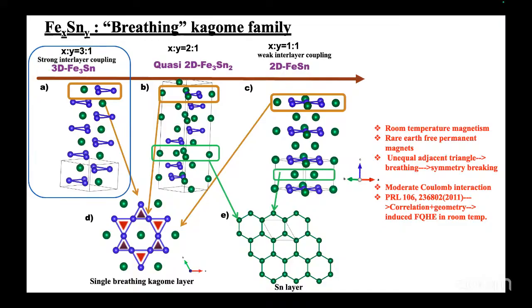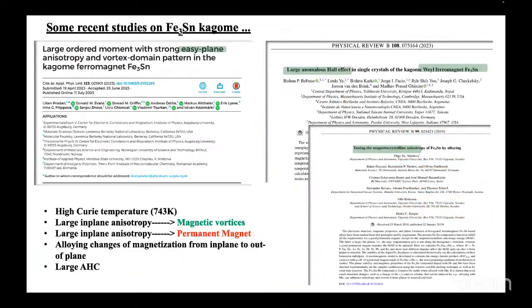Is there a conductivity measurement in this material? Is it the anomalous Hall conductivity? Yes. So this is the paper where they calculated the anomalous Hall effect for the single crystal, and both theoretically and experimentally, they get some difference.